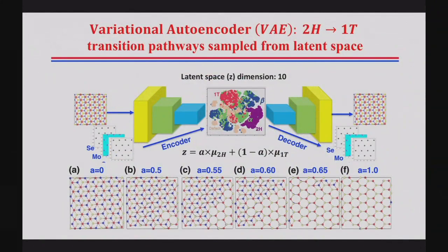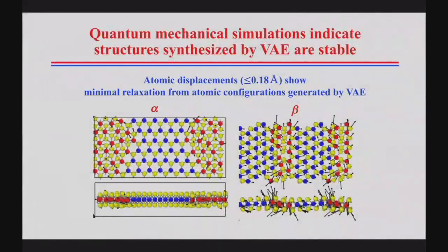And so we said, we want to find out how good are these structures synthesized by the variational autoencoder. So we did quantum mechanical calculations, which are the best calculations you can do, extremely accurate, to find out how robust are these interfaces and these devices. We did two simulations. In one case we put the alpha structure between 2H structures. In the other case we put the beta between 2H, and we did a fully quantum mechanical calculation on these systems. We found the atomic displacements were less than 0.18 angstrom, which is extremely small. In other words, what these quantum simulations are telling us is that machine learning is extremely reliable, and it can produce robust interfaces between structures, and it can be used to make new devices.